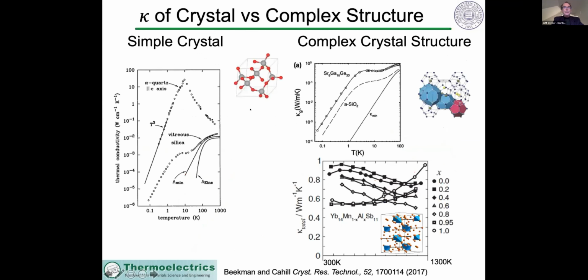Okay, so then another example is that in complex structures such as amorphous materials, one sees that the temperature dependence of the thermal conductivity can be very different. So for crystal material, we get the normal 1/T dependence, but in amorphous materials and also these complex structures, we get a relatively temperature independent conductivity. So something is clearly changing in the way heat transports in complex materials.